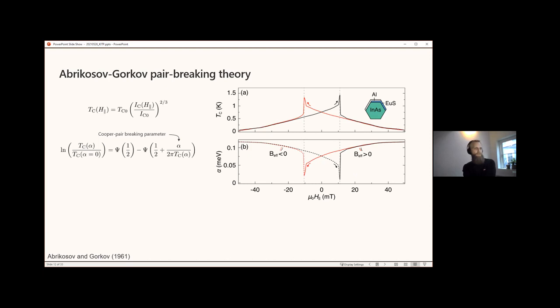Now, what do we do with this alpha? We can neglect, in the simple case, this is already slightly hand wavy, but we neglect the spin orbit coupling in the aluminum as it's a light material. And then we assume that this pair breaking parameter is given by essentially Zeeman energy, where the magnetic field is the effective field that we are interested in, essentially the sum of the magnetization and the parallel applied magnetic field.